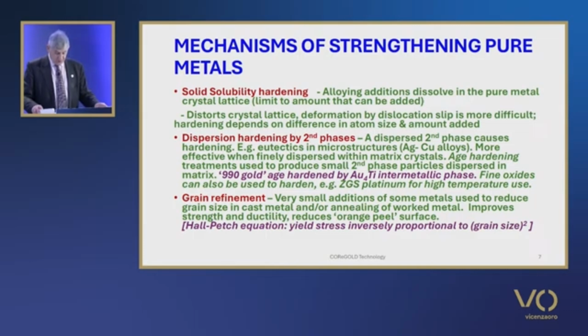It is also worth noting that dispersions of metal oxides, carbides and other ceramic particles can also be used to strengthen metals. An example in precious metals for high temperature application are the oxide dispersion strengthened platinum alloys such as ZGS or ODS platinum, where zirconia or ceria or similar oxides are used. Microalloys, where very small alloying additions result in considerable hardening, also fall into this category of hardening by dispersed phases.